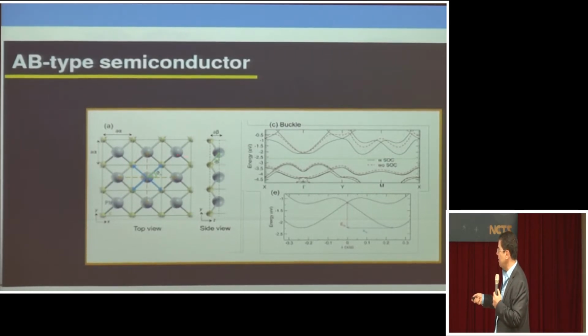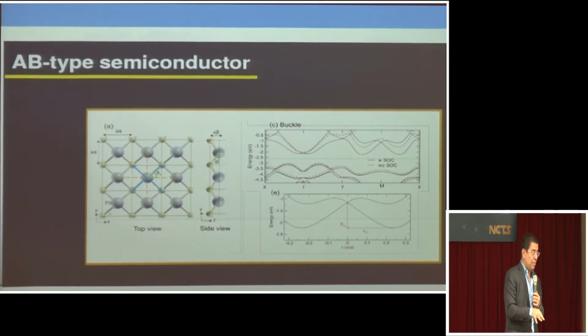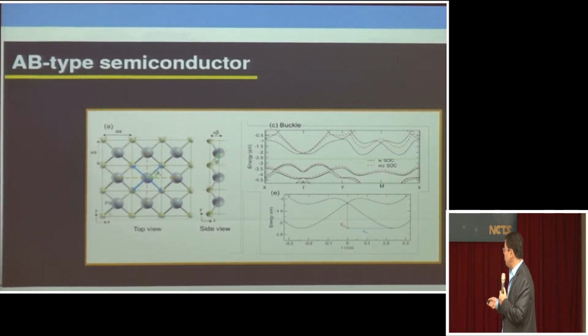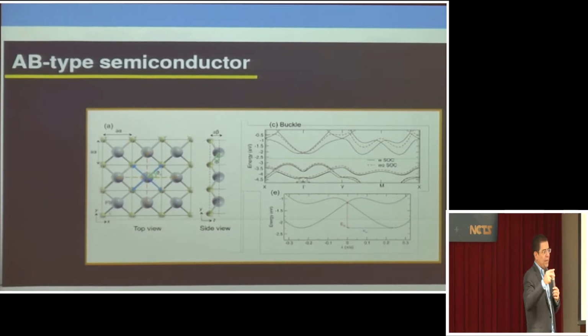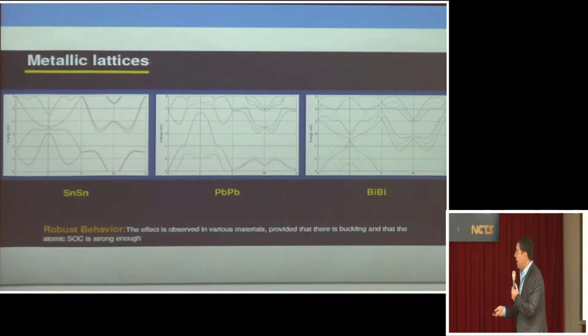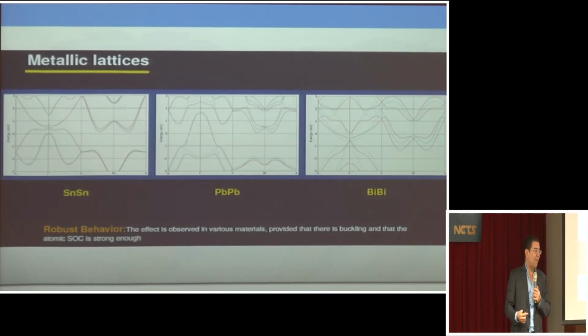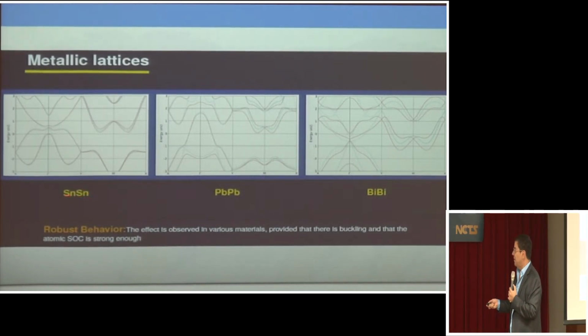This is a square lattice, and you have this up and down structure. And the interesting thing, you look at the band structure, all these materials become semiconductors. But the interesting thing about these materials is that they have this level crossing here, which actually comes about purely from the spin-orbit coupling. It's the result of this spin flip process I was talking about. And actually these are different. Of course, numerically I can make whatever I want, like tin, lead, bismuth, and this is the band structure that you get.